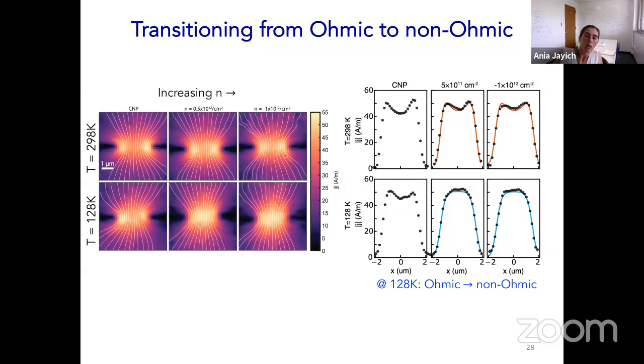As we increase the density, we see that the flow patterns change a little bit, but overall it still looks ohmic; we have the presence of these ears. We see that the flow is ohmic, maybe a little bit less ohmic, as one might expect actually. But importantly, as we go to low temperature at 128 Kelvin, where we've now increased the momentum relaxing length, to the point where the electron-electron scattering length can drop below that of the momentum relaxing length, we see that away from charge neutrality, we see these profiles that are consistent with non-ohmic flow.